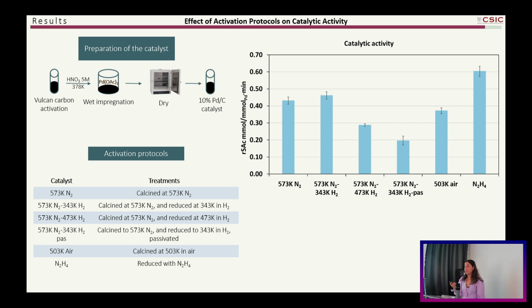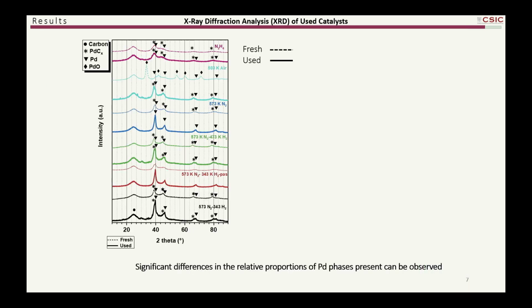that we obtain the best results with the catalyst reduced with hydrazine and with the catalyst reduced with hydrogen at 343 Kelvin. So these results suggest that the species forming in the reaction process play a role in the catalytic activity. For that reason, we decided to carry out different characterization techniques, and I'm going to explain one of them.